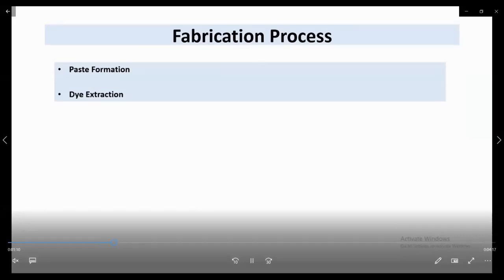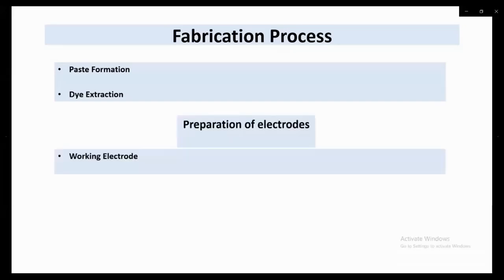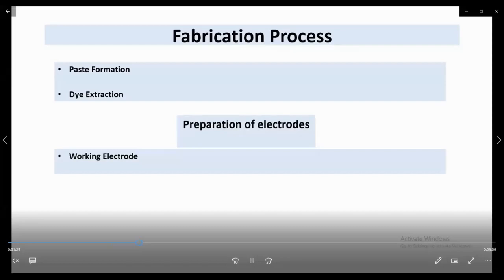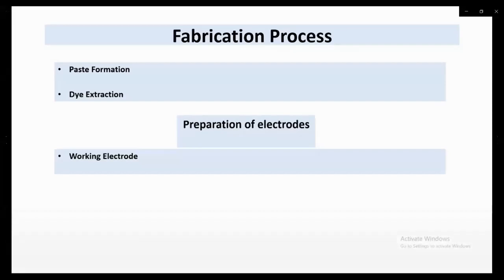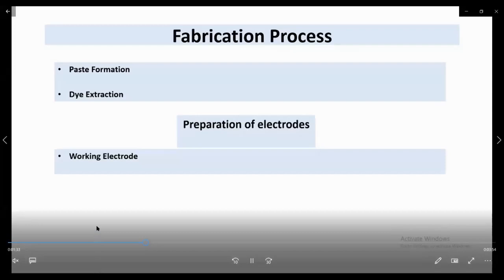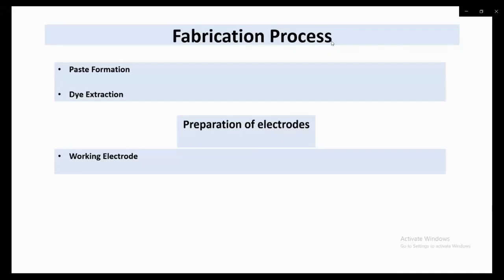So, first we will see the working electrode. For the preparation of the working electrode, FTO glass plates were used and the TiO2 paste was coated on the FTO glass using the doctor blade method. The FTO glass was heated for 10 minutes and then both slides were heated at 300 degrees Celsius for an hour. Then these FTO slides were immersed in the natural dyes and kept for 48 hours. This is now known as the working electrode.